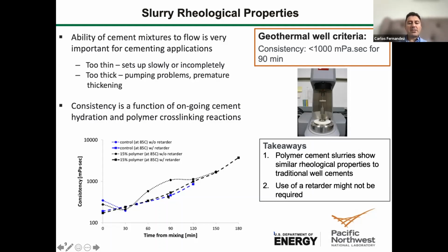The actual polymer itself, the polymer precursor, as well as the polymerized polymer, forms what we believe is a shell, or semi-impermeable shell, around the anhydrous components of the grains of the cement, and reduces or retards the hydration process. Eventually, the consistency increases, but you have workability for at least 120 minutes. 90 minutes is what is required for a geothermal wellbore cement.